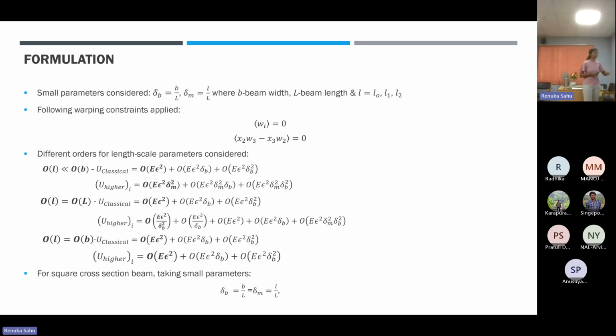We need to understand what order the material length scale parameter can take. We've taken three different cases. In the first case, the order of the length scale parameter is much less than the order of the width of the beam. For this case we get the following strain energy orders: the classical strain energy order is given, and all the higher gradient strain energies associated with gradient strains come to be one order higher than the classical strain. So this is one particular case.